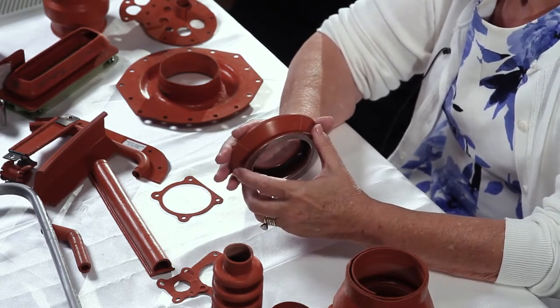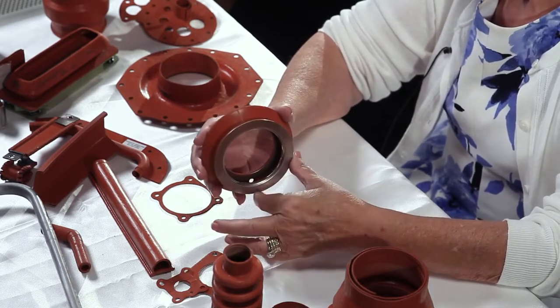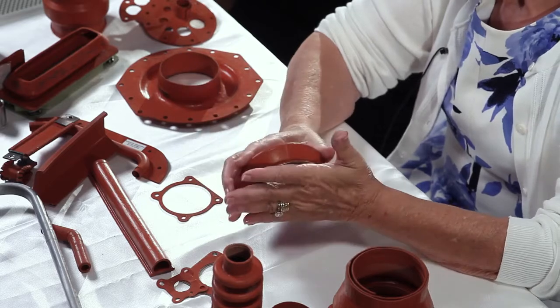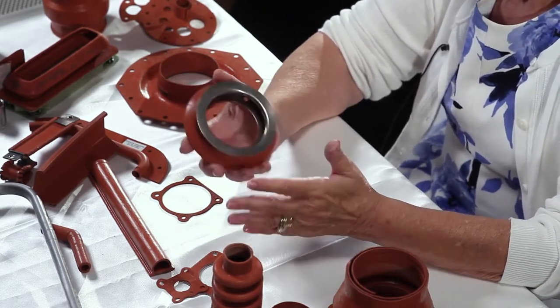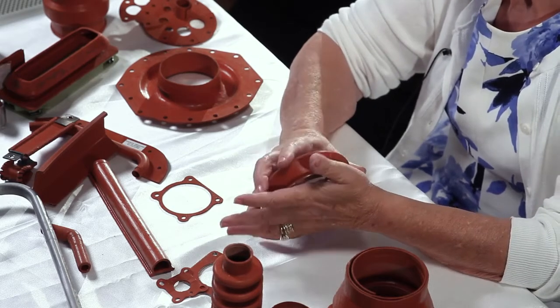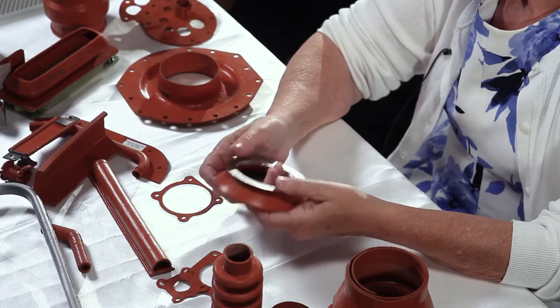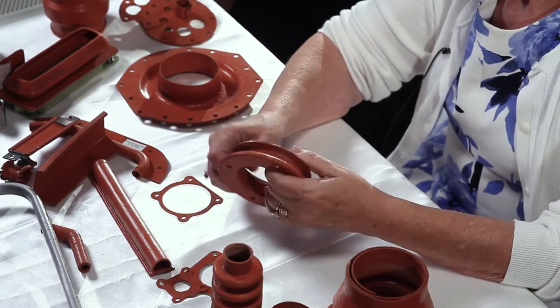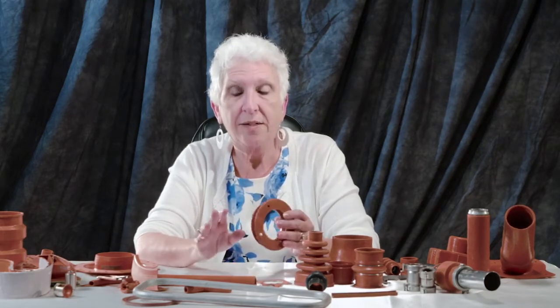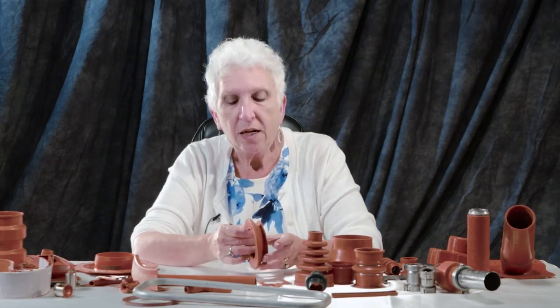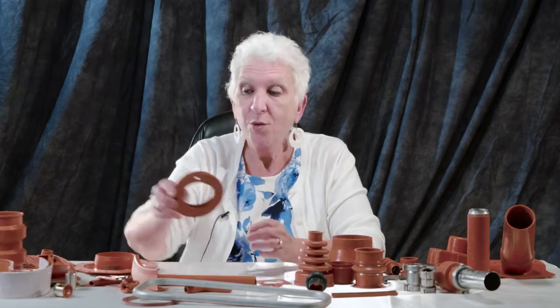The B-stage material is the adhesive. It can be cut to fit the exact size, so there's no cleanup. We clean the surface. We usually use a Dow 2200 primer. We make sure we have good surface contact by using something like an ink roller and heat it to 300 degrees for 3 minutes. There's nothing else required. It doesn't require special temperature conditions. It doesn't require a 48-hour wait. It's done. We get such a good bond that it required 80 psi to peel our material off of a sheet of untreated titanium. And that test was done in the shop on the shop floor at McDonnell Helicopter, where we used a hot air gun to achieve the bond. So it's a pretty strong bond.